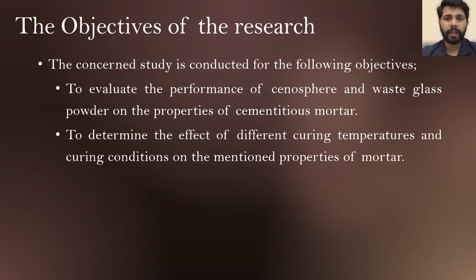Now the objectives of this study. The objectives of this current research are to evaluate the performance of Cenosphere and waste glass powder on the properties of cementitious mortar. In this study, Cenosphere and waste glass were replaced by cement in a varying percentage of 0 to 20% to evaluate their performance based on different curing temperatures and curing conditions. Two different curing temperatures, ambient and high temperature including 80 centigrade, were applied with two different curing conditions, such as water curing and air curing.